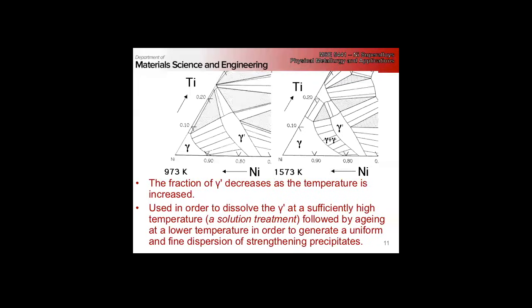We have a solvus, right? So basically, in the ternary, we can go super solvus, dissolve the gamma prime, and then precipitate out a uniform and fine dispersion.